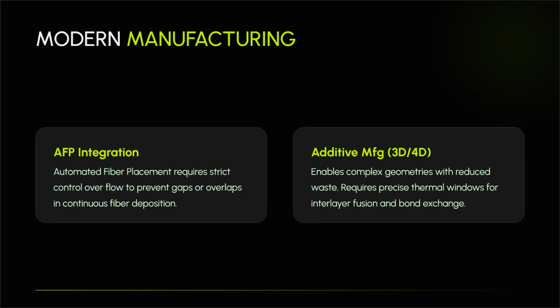Beyond liquid molding, we must evaluate modern advanced manufacturing methods, specifically automated fiber placement, or AFP, and additive manufacturing. Automated fiber placement is crucial for scaling large aerospace structures, but it demands strict control over resin flow and tackiness. If the Vitrimer matrix relaxes too quickly or flows unpredictably during the continuous deposition of carbon fibers, it can introduce geometric defects, such as gaps, overlaps, or fiber waviness.